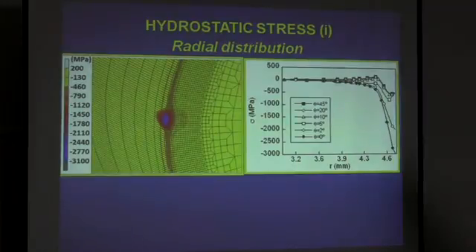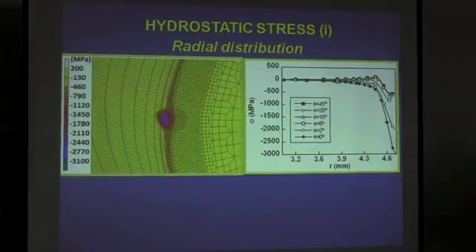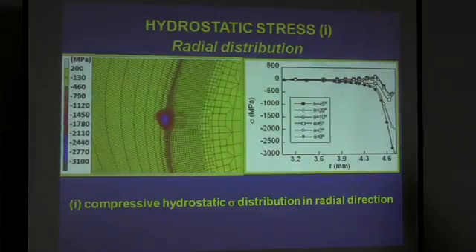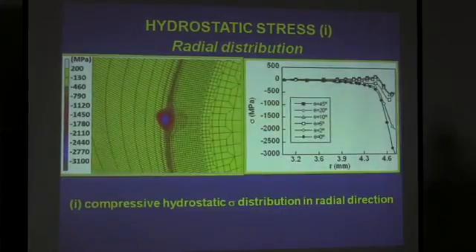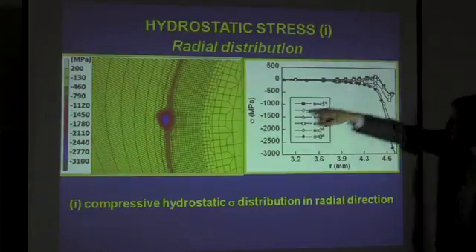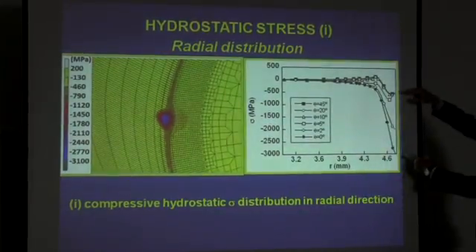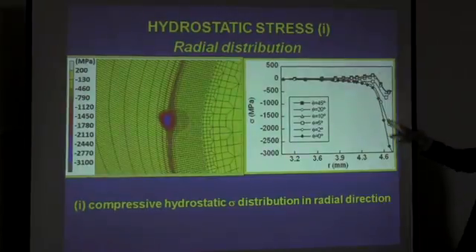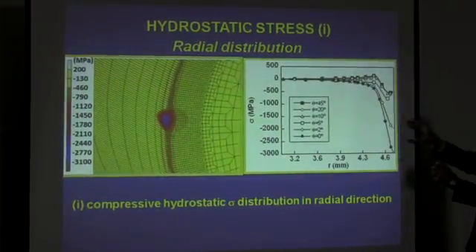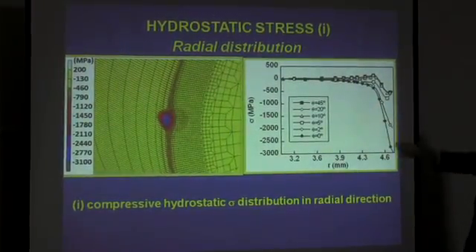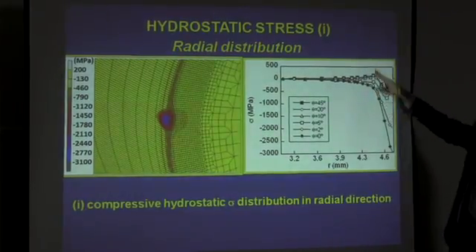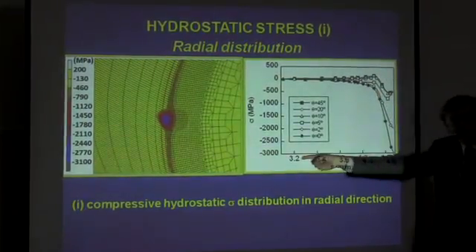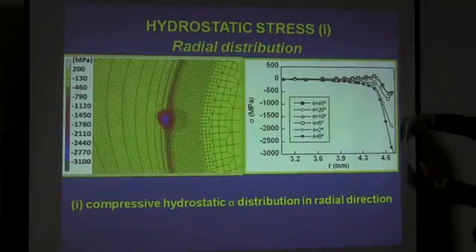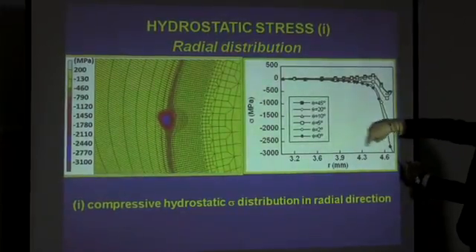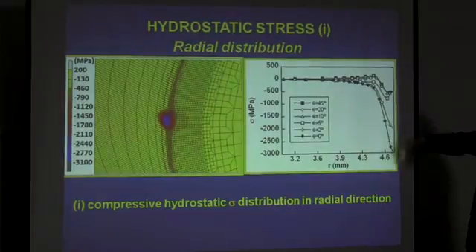And with regard to radial distribution of hydrostatic stress, which is 1/3 of the trace of the stress tensor, we have similar distribution. Compressive hydrostatic stress, that's the key relevant variable for hydrogen diffusion. It means that there is an inward positive gradient. Hydrogen is pumped from the surface to the inner points because of positive inward gradients, negative radial gradients, but positive if we consider the X variable, the opposite from the surface to the inward point.